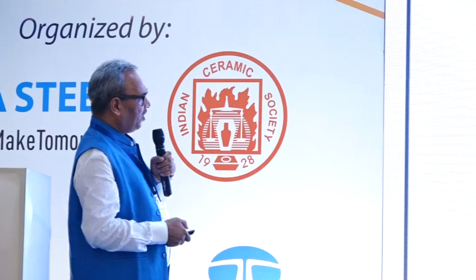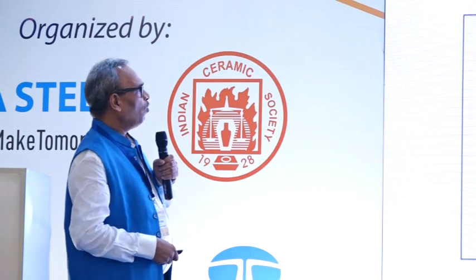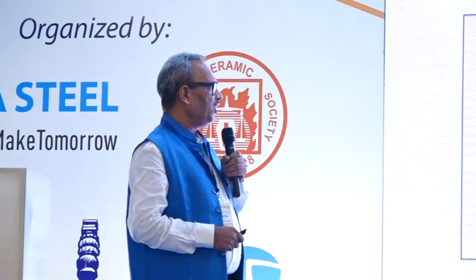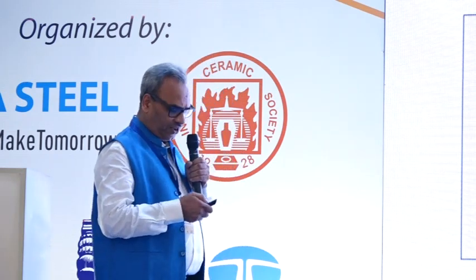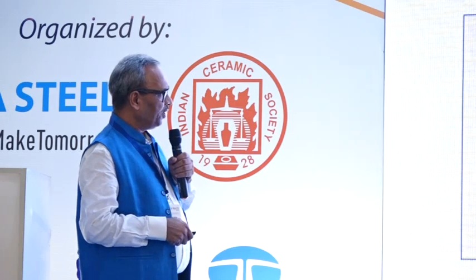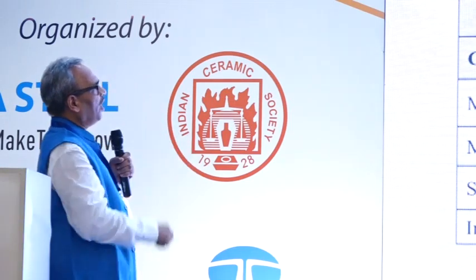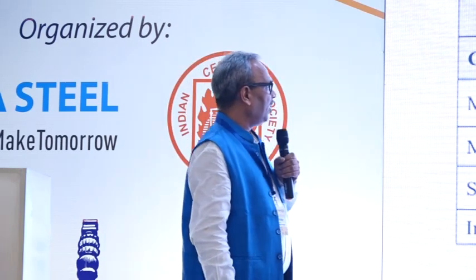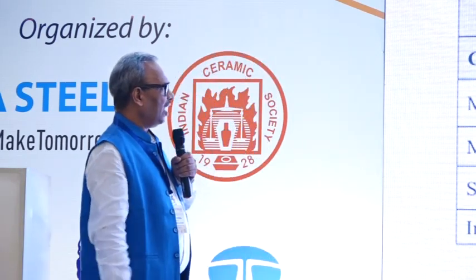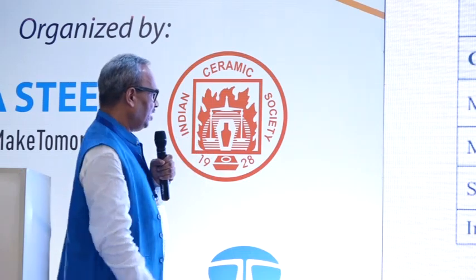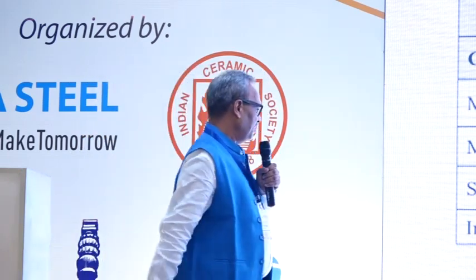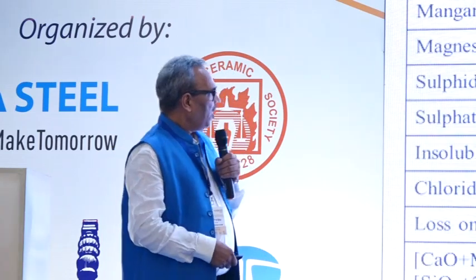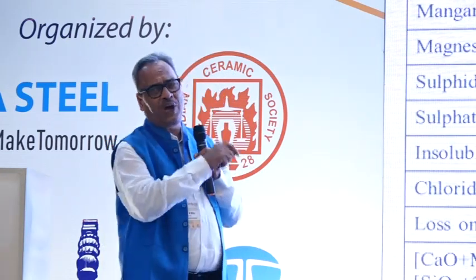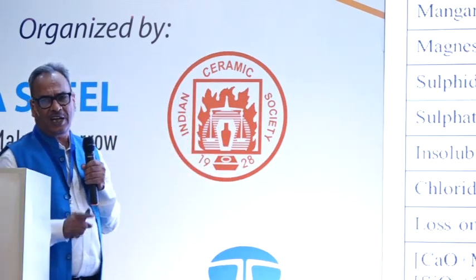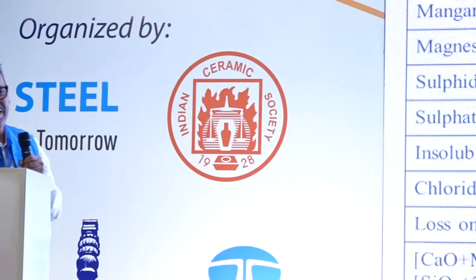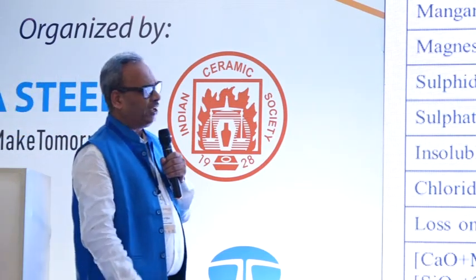So sector-wise utilization, I am skipping it. Now, what are the present provisions in Indian standards for utilization of slag in the construction sector, particularly in cement and concrete? We have IS 12089:1987, a specification for BF slag for cement production, in which glass content should not be less than 85%. We have a specification for ground granulated blast furnace slag, which can be used directly in concrete production, and it can also be used in PSC production as a blending material.